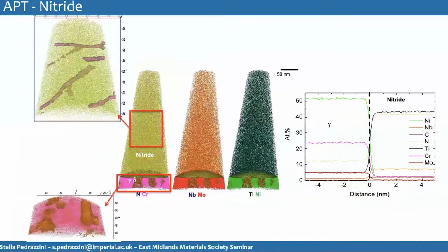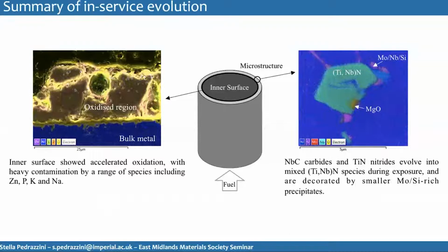The other interesting thing that we saw is that all of the dislocations within the nitride were very, very chromium rich. So all of these lines that we can see in the nitride are chromium-rich dislocations. So that's a sign of the initial dissolution of the nitrides and evolution of the composition. So this must have happened above 1,000 degrees. So we can tell that they've pushed Inconel 625 above 1,000 degrees, which is not really certified to go to that kind of temperature. And that's the conclusion of that work.